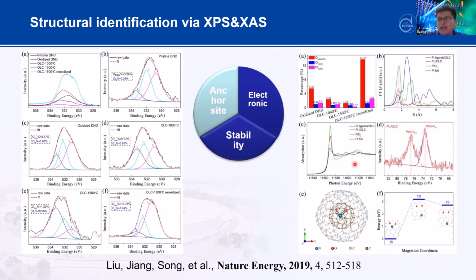You see clearly, we can say that the Pt in there is a single atom. They do not have the Pt-Pt bond in there. In most cases, they are bonding with the oxygen. So by this characterization, we really can give the atomic model. So we set the atomic model like this. In here, we put the Pt combined with the oxygen group in the carbon onion.